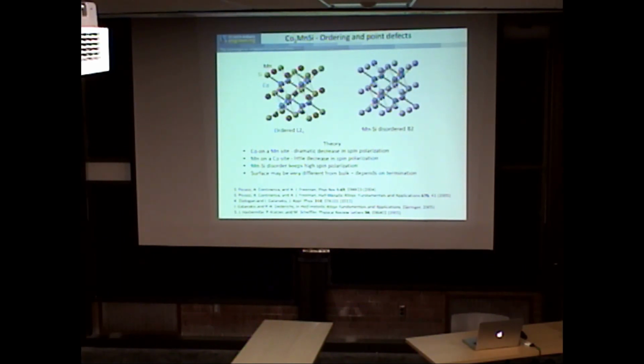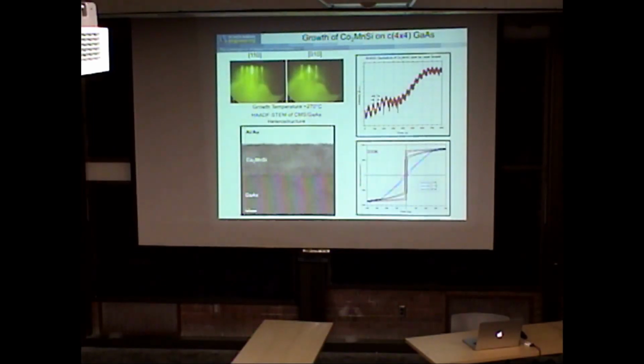Of course that's all about the bulk. For the surfaces, in theory, it's very important what the surface termination is, whether or not you keep the spin polarization at the surface. So here we've actually grown cobalt manganese silicon. This is reflection high-energy electron diffraction. These streaks say it's relatively flat and nice and crystalline. It's grown at up to 170 degrees C.